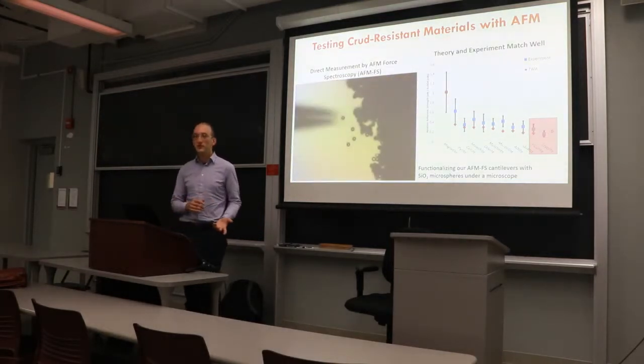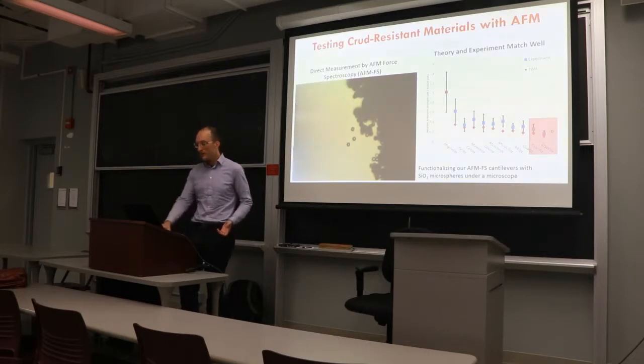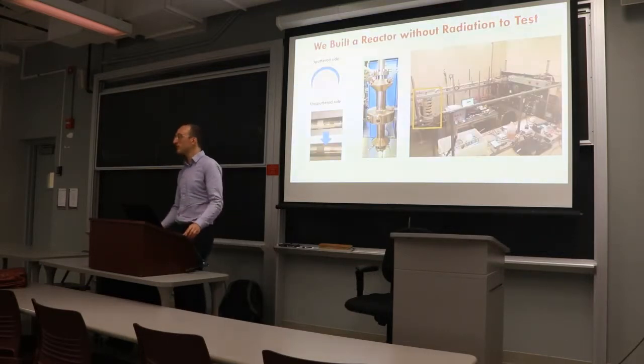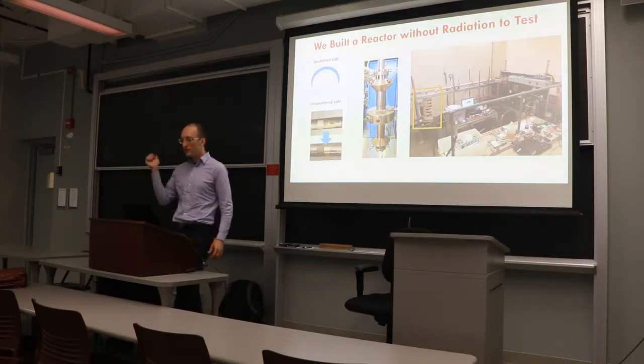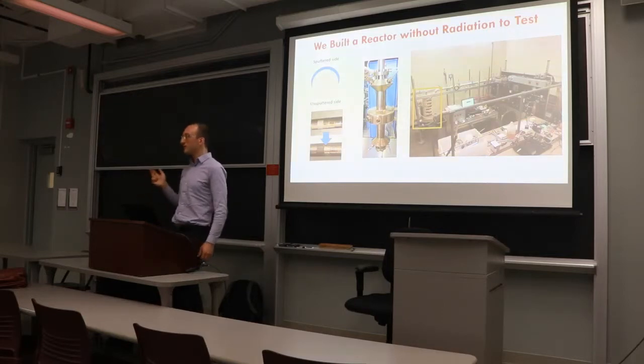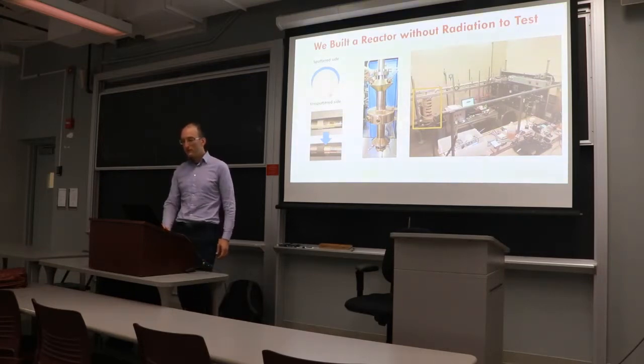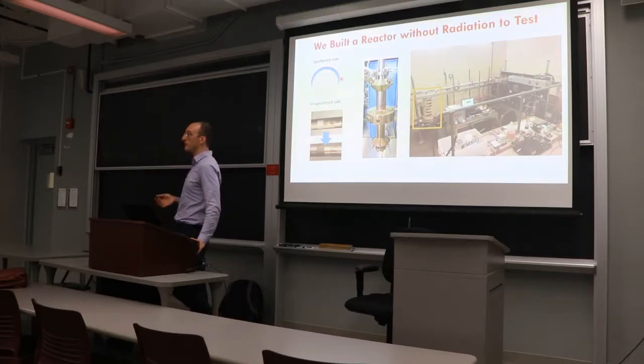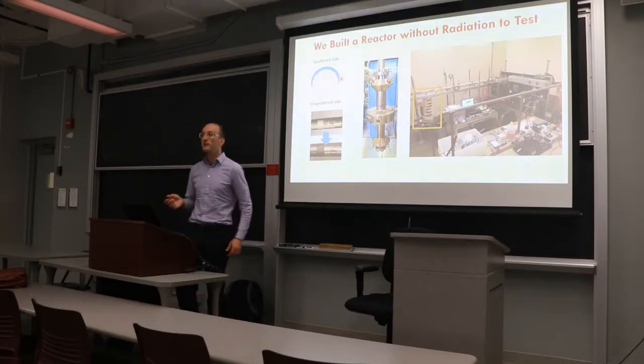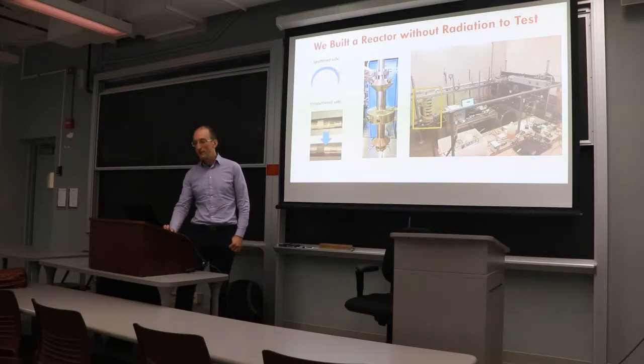But it's not just enough to do this in a room temperature AFM. So we built the first monstrosity of our lab, the Crud Loop, which is a reactor without the radiation. So it's just a big flowing loop that goes to the same pressure, temperature, heat flux, flow rate, and water chemistry as you get in a reactor, but no radiation. And we slide rings of zircaloy onto our heating rod and coat half of them in our potential crud-resistant material. So this way we have a built-in control. The top half has our slick coating, and the bottom half is bare zircaloy.